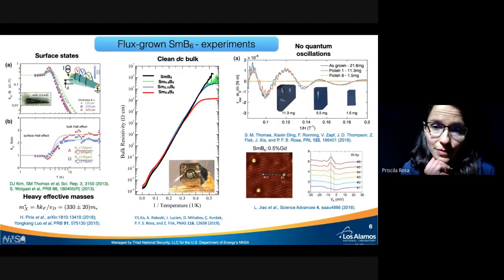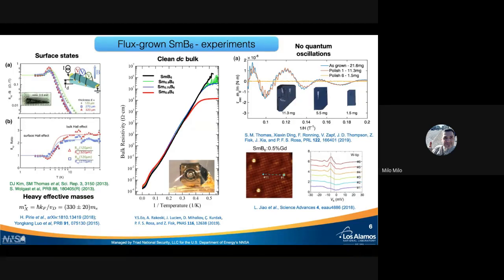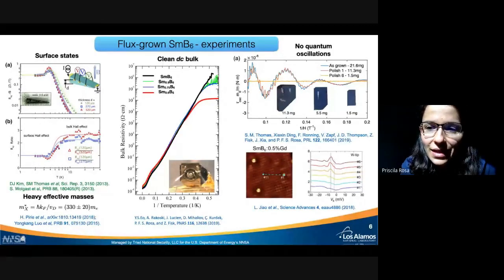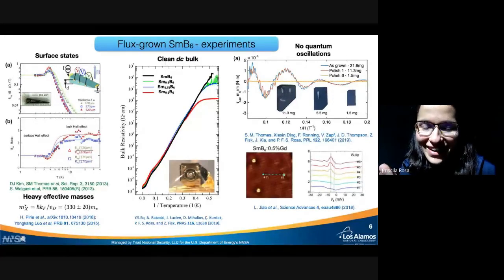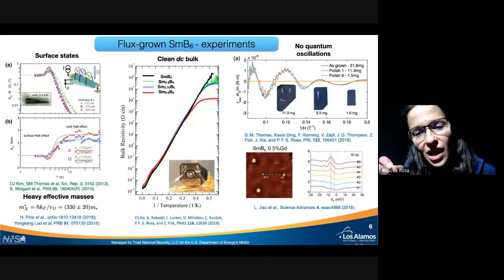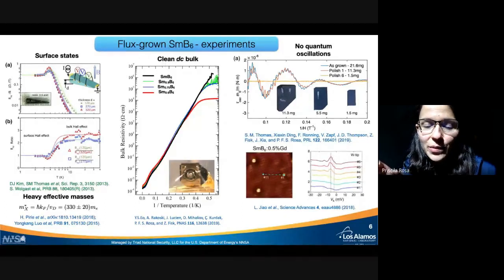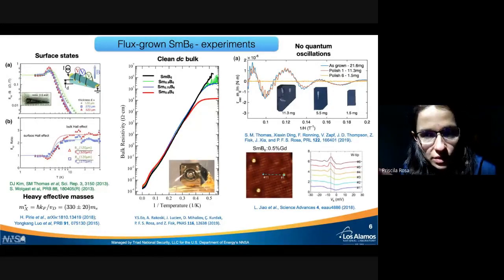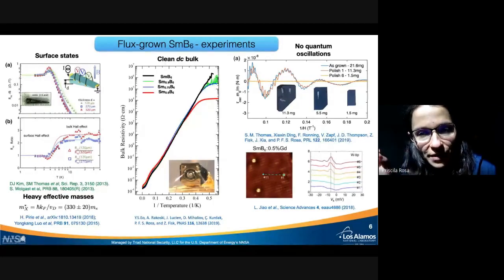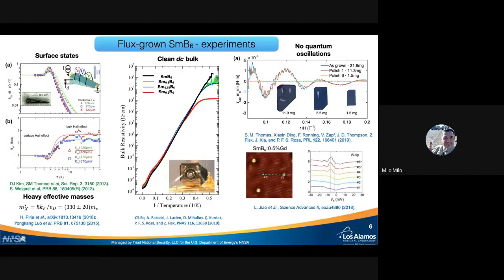From aluminum. Just from the aluminum. And why do they disappear then as you have thinner and thinner samples? Because we are removing the aluminum. In the first picture here, there are clear aluminum deposits that I mentioned. They kind of look like a smiley face. Those silver-ish parts are actually aluminum inclusions. As we go to the second sample, we can still see the aluminum inclusion there, and we still see quantum oscillations. But then the third sample is a very, very thin sample. We see no aluminum, and the oscillations are completely gone. That's the yellow data set. So you had metal, and therefore okay. Exactly. You did have quantum oscillations, but not from samarium hexaboride.